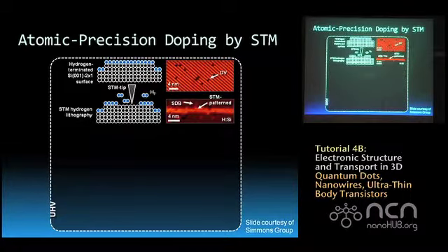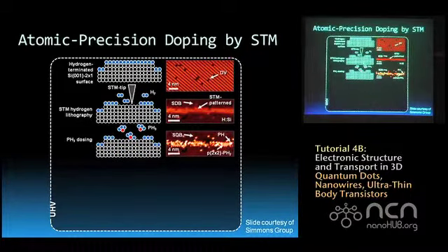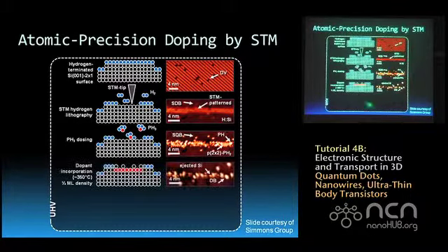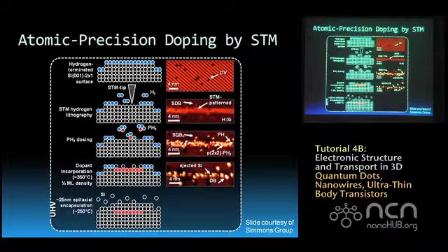Okay? And then you come in with phosphine, and the phosphine actually sits down on that depassivated surface. And it can't sit down where it's passivated with hydrogen. And then you can overgrow this again with silicon, and you start to bury the phosphine under the surface. And that sounds pretty crazy, but people actually do that.